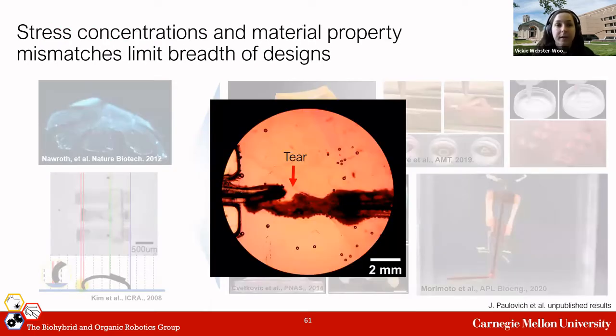This is in part because of part of the research that somehow seems to never end up in the papers, right? And that is high failure rates, possibly due to stress concentrations between very soft muscle tissues and any stiffer robotic structures. The muscle has a very low modulus. And so you can see that when we try to attach it to more rigid structures, that can increase the likelihood of getting these tears in the tissue.